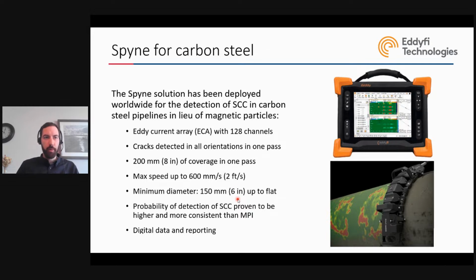For the probability of detection, we've done a lot of studies and published a lot of papers. We have shown that the POD was higher than magnetic particles because this is an automated scanner. You don't have to rely on the visual interpretation of data, or on lighting and all that. So it's just an improved version of magnetic particle in that regard. And finally, you also get digital data, so if you want to look at the data 5 years later, it's very easy to find it back and interpret all the data.